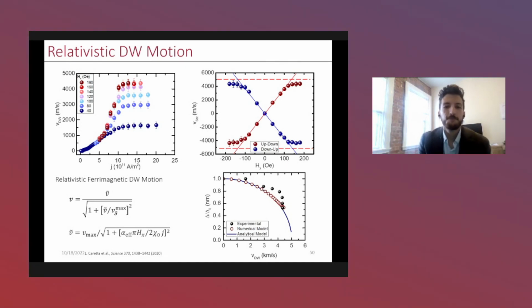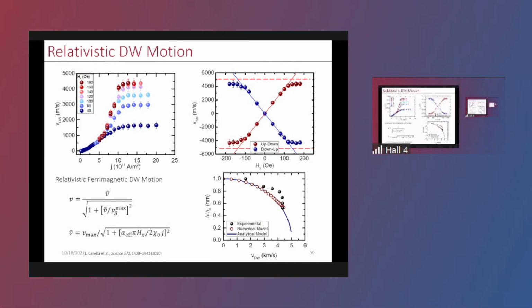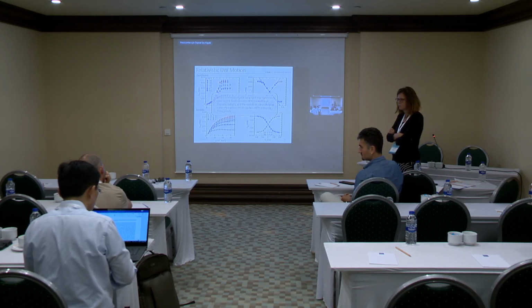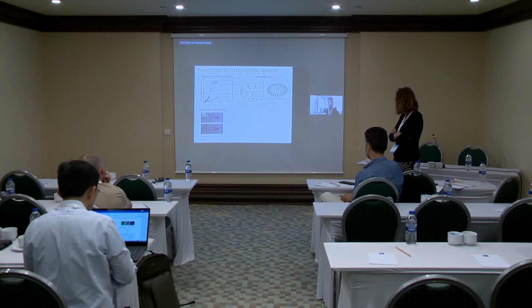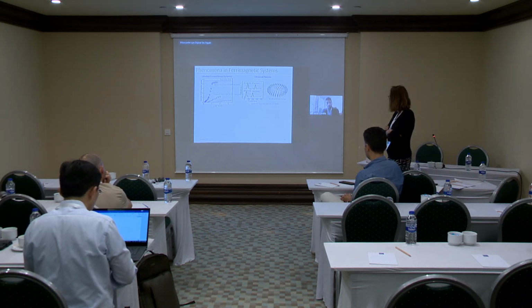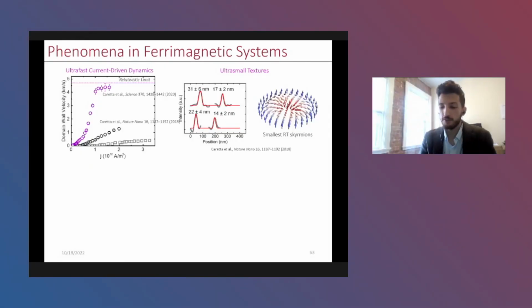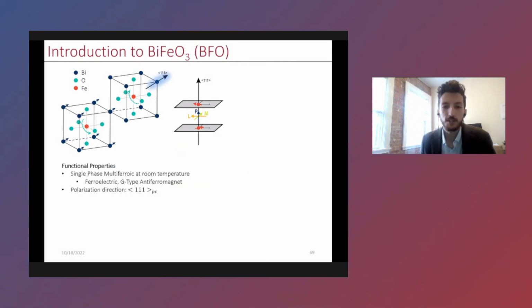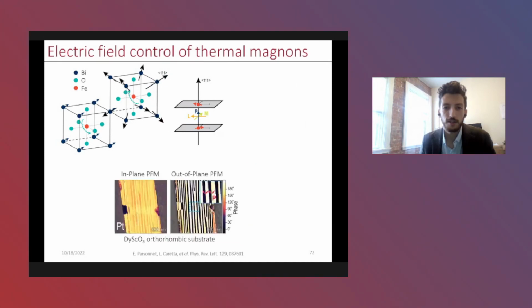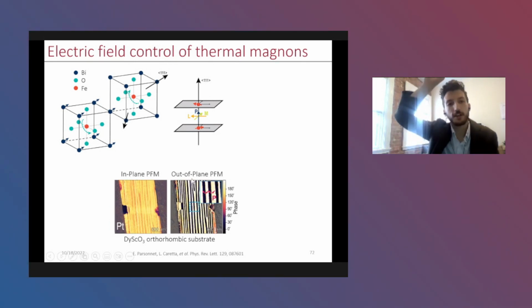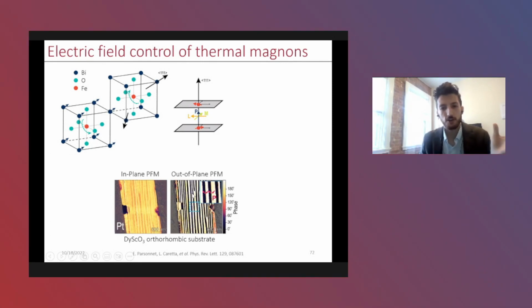Okay. And in the measurements of the magnon in the bismuth ferrite, you also measure the first harmonic. You say that you thermally excite the magnons, but do you see anything in the first harmonic measurements? Yeah, good question. We measured the second harmonic in the experiments that I showed. If we measure the first harmonic, we don't see anything, and the reason has to do with the domain structure. Between the two electrodes, these domains are oriented parallel to the electrodes, and these domains of different polarization of bismuth ferrite are elastic in nature. So there's a structural change across each of these ferroelectric boundaries, and we expect that this is causing a lot of magnon scattering, and so you don't see any first harmonic.